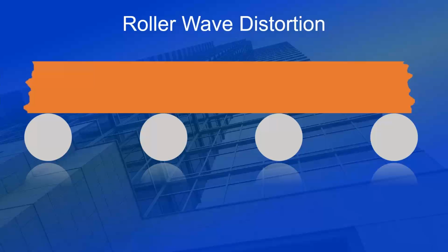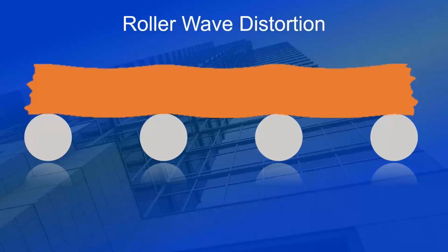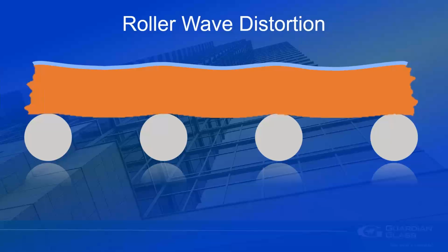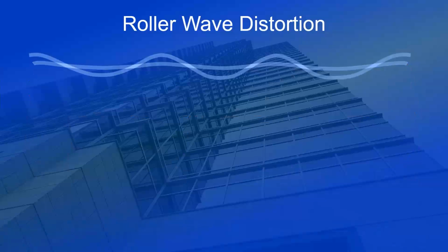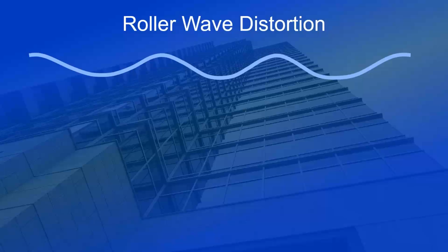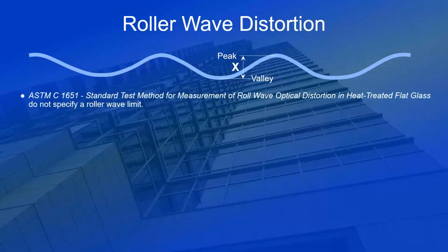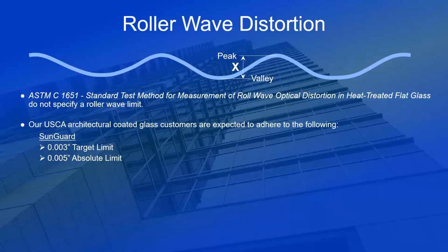When the glass is heated up to around 620 degrees Celsius in the tempering oven, it becomes ever so slightly soft. Each one of those spheres represents the roller wheels that move that glass through the furnace. If we were to look at the top plane of the glass and just focus on that top plane for a moment, and we're going to increase its amplitude a little bit to make this discussion easier, we're looking at peaks and valleys. It's the reflection of light off of these peaks and valleys that the eye picks up when we see roller wave distortion on buildings.